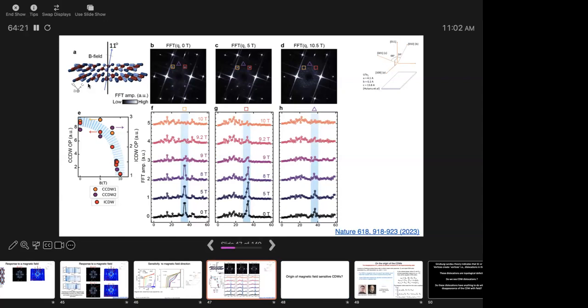It's around 10 Tesla. And now, not only do the three peaks get suppressed, this is 0 Tesla, 5 Tesla, and 10 Tesla. At 10 Tesla, all of these three peaks are gone. So this is 0 Tesla, you see the peak, 10 Tesla is gone. So this is this peak. Same here. This is 10 Tesla, right? This is within the noise, mostly gone. All three peaks are almost gone at 10 Tesla.